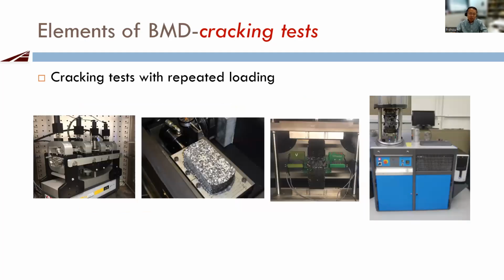And talking about the repeated load tests, this is the beam fatigue test. It's a long beam, 15-inch long beam. It's very difficult to make the beam specimen. And this is a Texas overlay tester. You have to make tall specimens, chop from the top and bottom, and chop the left and right to get the small specimen for the overlay test. And for the overlay test, you have to glue it, and make sure the glue is dry before you test it.